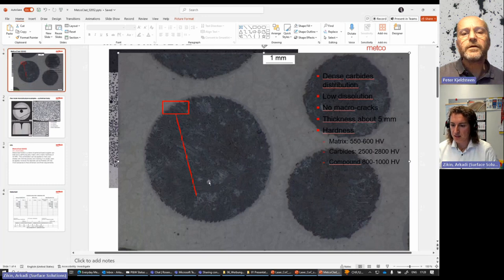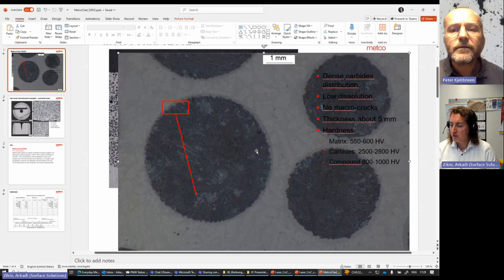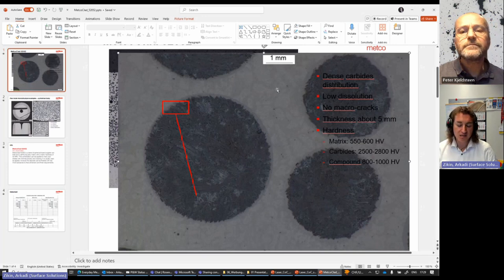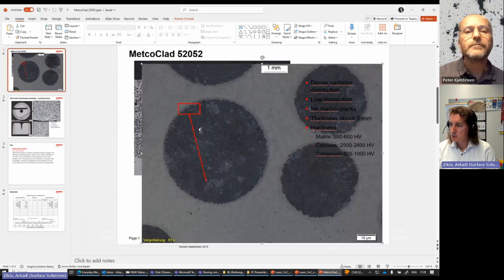I don't know how it is in English, but fused tungsten carbide is the proper name. What happens typically? You have a dendritic nickel self-fluxing matrix. You can see it here, and in any conventional process, typically you melt those carbides so much that they actually recrystallize and build eta phases inside the microstructure. Here you see a very beautiful, maintained rounded particle, which was an initial particle, and there is almost no diffusion zone of the tungsten carbide, which helps you to keep the carbide hardness.